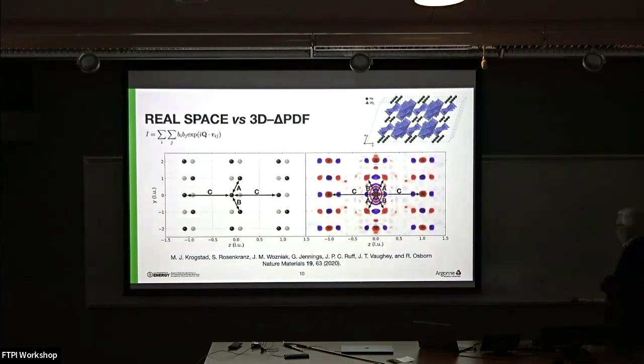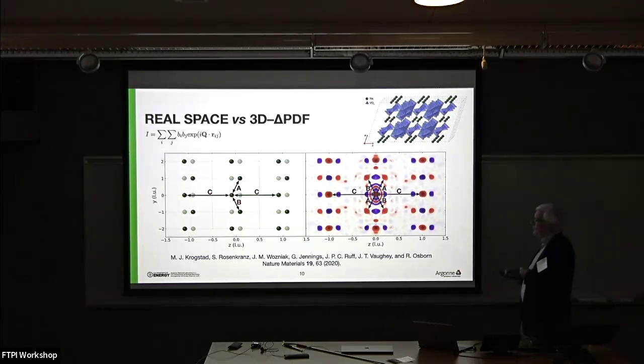So for instance, this nearest neighbor vector is blue. That means it's less probable than the average, whereas this next nearest neighbor is red. That means it's more probable than the average. You get these three-leg ladders in the PDF because we're summing over the probabilities for all the vectors from all the origins. So the origin could be on the left leg next to the right leg, or on the right leg next to the left leg.